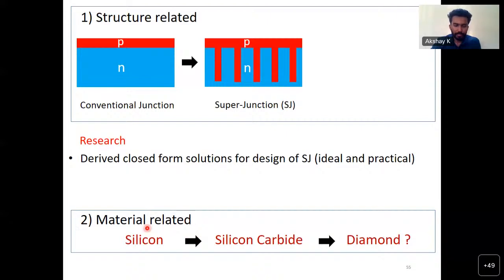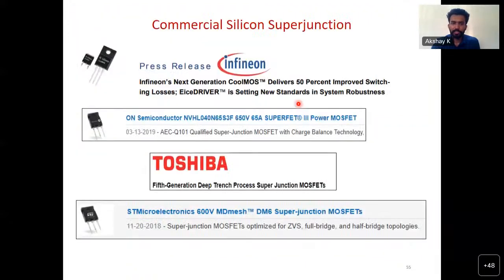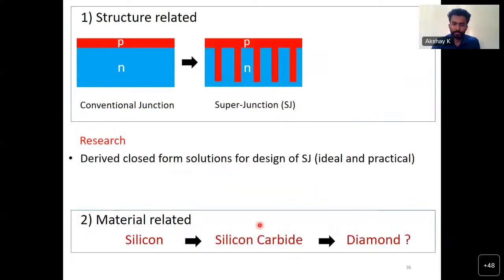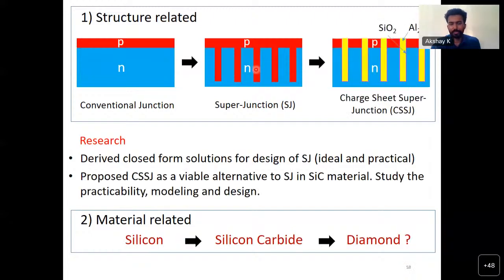And then, as I told you, things have been moving from silicon to silicon carbide. Initially you had PN junctions in silicon, then you had power diodes in silicon carbide, but silicon superjunctions have not been properly or commercially transferred to silicon carbide based superjunctions. You can see a lot of silicon superjunctions in the market from all the famous companies, but silicon carbide versions of the superjunction are still not up. It has been demonstrated academically, but there are a lot of challenges associated with making the P pillar for a silicon carbide superjunction. So that's the difficulty with silicon carbide based junctions.